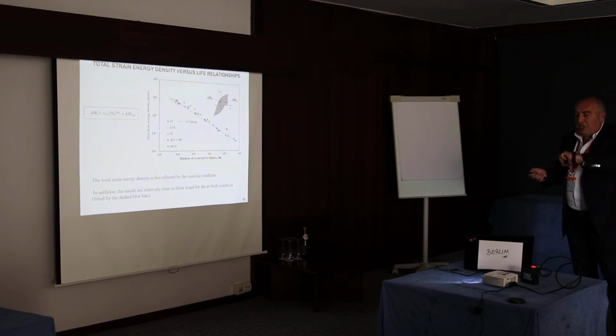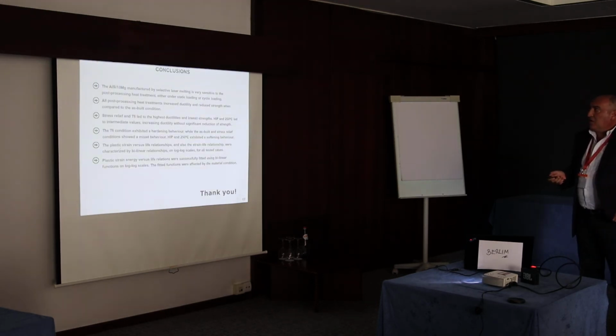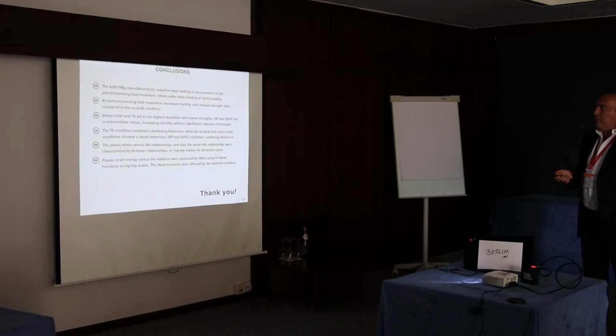So, finishing, drawing some conclusions: the aluminium silicon 10 magnesium manufactured by selective laser melting is very sensitive to the post-processing heat treatment, either under static loading or cyclic loading. All post-processing heat treatments increase ductility and reduce strength when compared to the as-built condition. The stress relief and T6 led to highest ductilities and lower strengths. The HIP and the 250 led to intermediate values, increasing ductility without significant reduction of strength.